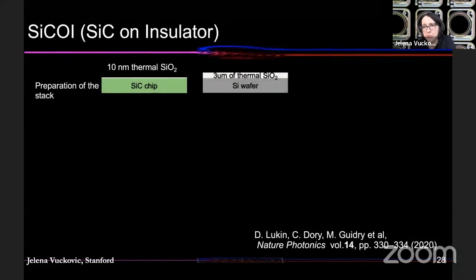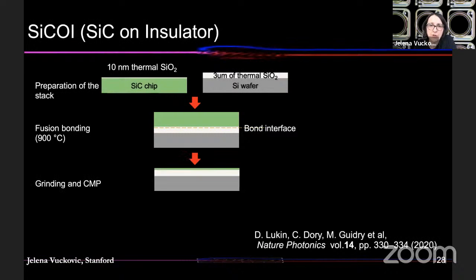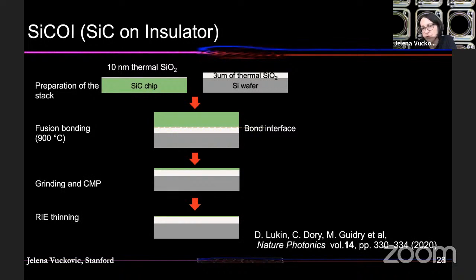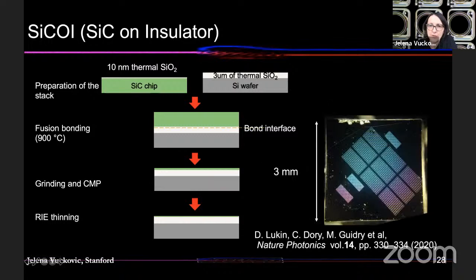So we had to come up with a process to make thin film silicon carbide on insulator, and we just start with silicon carbide wafers. We bond them onto oxidized silicon and then grind, thin, and then do fine thinning, and that way we end up with chips that are pretty uniform, and we can make a lot of photonics within these several millimeters, but we can also scale this up to larger wafers if needed, although that's not something that we need for our own fabrication. And this process, which looks quite simple, is crucial for enabling these high purity, pristine films of silicon carbide on insulator.